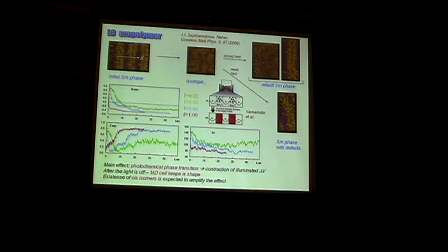And after some time, the smectic phase is destroyed due to reorientation of azobenzene. And if we wait longer and if the strength of the field is enough, then we see that the smectic phase is rebuilt in other directions. So this is the same view as here, but here we turn the box to other directions. So we see the same smectic phase but being reoriented.